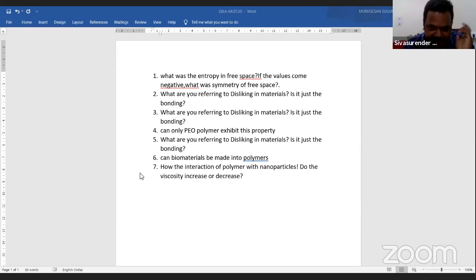And the next question: with the interaction of polymer with nanoparticles, does viscosity increase or decrease? So that is what I told you. You can achieve both cases, right? You can make it increase, or you can let it decrease. Now, if you have a nanoparticle where you have attached these polymers, for example, since I was showing, this was based on my work, where we used gold nanoparticles and used polystyrene to graft them, right? These polystyrene chains are ended with a thiol group, and then this is a simple physical adsorption, right? Because thiol has a higher affinity constant with the gold, so they can just get completely attached.